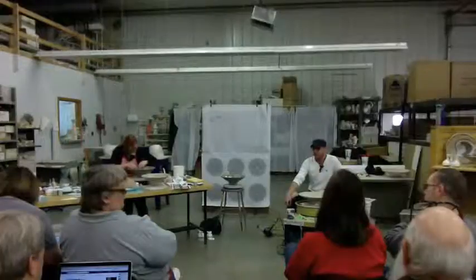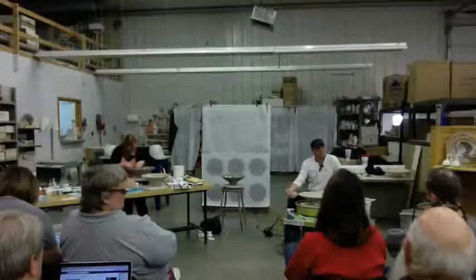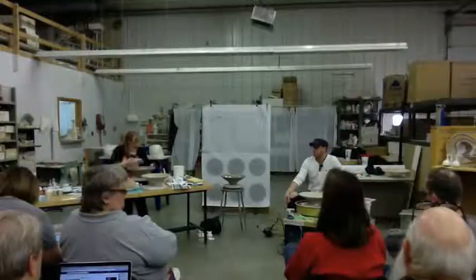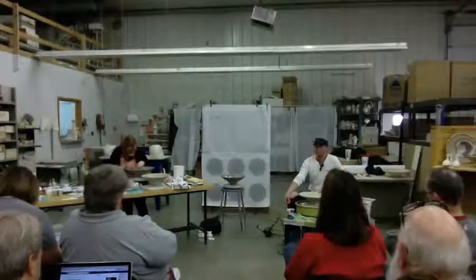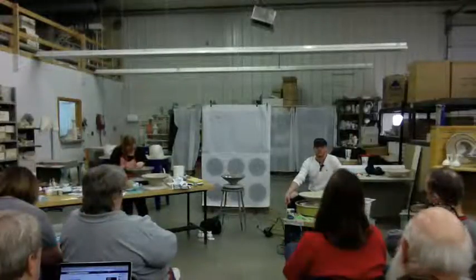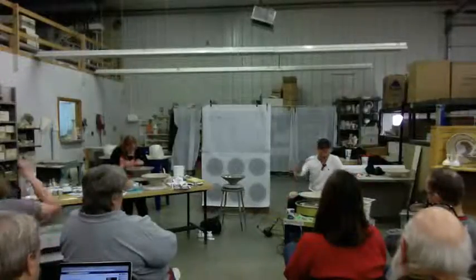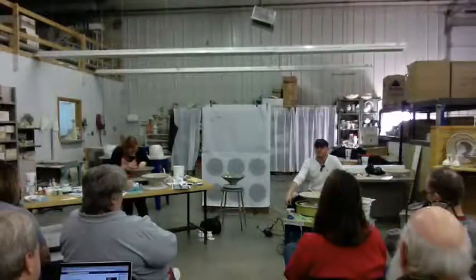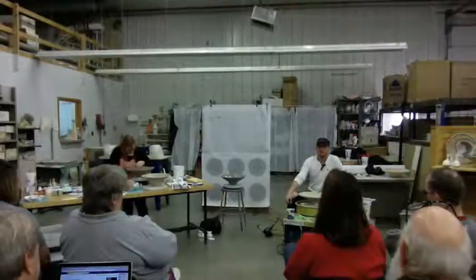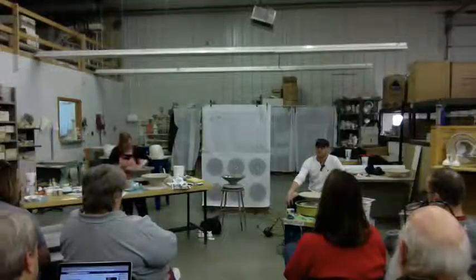I just don't like water going into something that's still breathing, because if it absorbs under that clay or adheres under it, it can create bacteria, mold, or pop off. I know in grad school, I had all my pieces thrown, and then half of them had limestone in them. So there's lime popping off all of my work. If you ever have a little piece blow off and there's a little white center inside of that, you see, limestone. So you'll find them by washing your pieces off to glaze, because that will absorb that water. I've had that happen to some of my beautiful pieces.